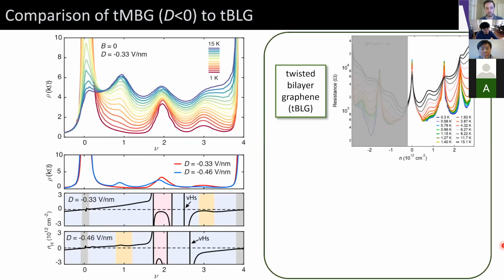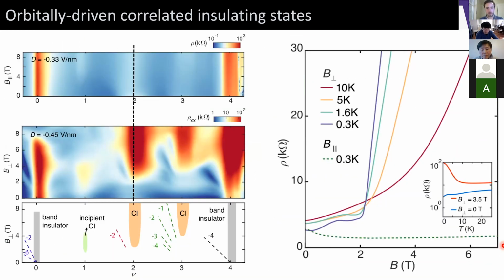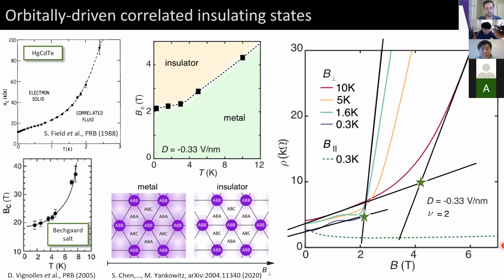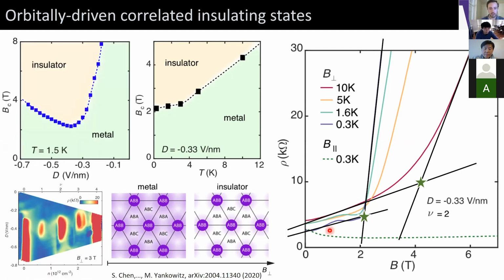Now, when we apply a perpendicular magnetic field, we have an orbital effect which confines the local density of states more tightly around these ABB stacked regions. And effectively, that can boost the effective strength of correlations and lead to some insulating ground state above a critical magnetic field. And the cool thing in these systems is that we have quite a bit of flexibility to tune these. So, we can modify these states by applying an electric field, and at a fixed temperature, we can also create a phase diagram where we tune this crossover point between the metal and insulating ground states as a function of the electric field.